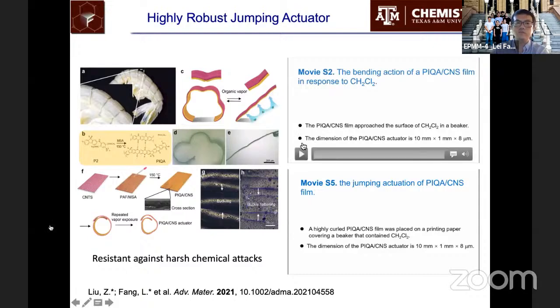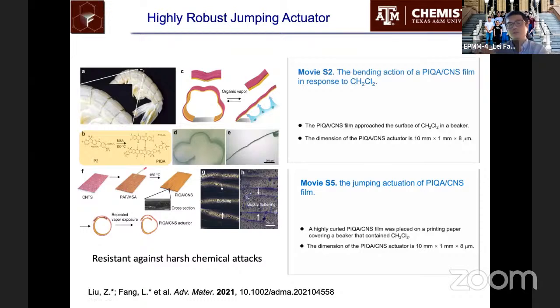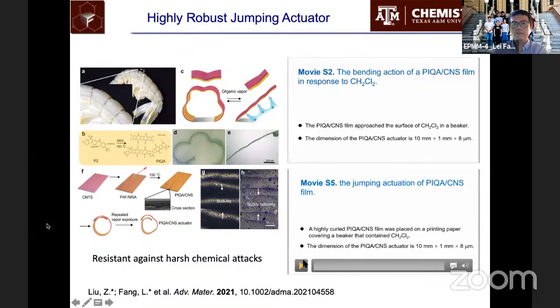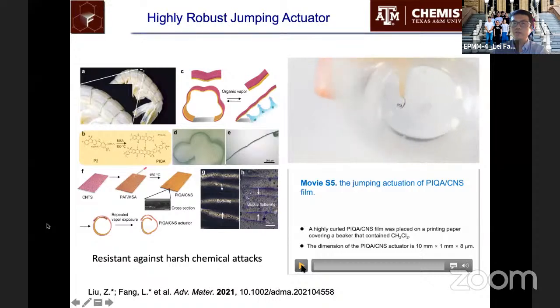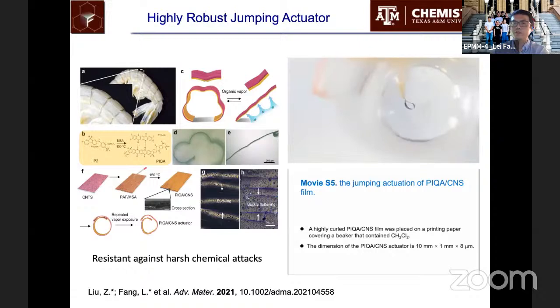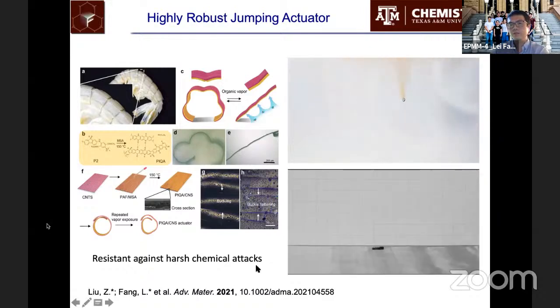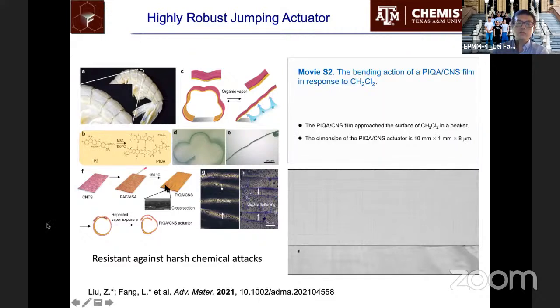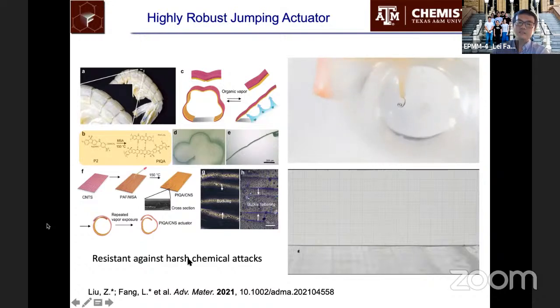For example, this actuator. This is a collaborative work where we put this ladder polymer on top of carbon nanotube sheets so that you could utilize the different expansion coefficient of the material versus carbon nanotube when you expose it to solvent vapor, and then that gives you this actuating process. I think this one shows that if you expose the film to external solvent, you can see a very big change of the shape due to the actuation process. And this could actually jump by itself due to the very strong force generated by this actuation. A very important aspect of this material is its resistance against very harsh chemical attacks, unlike most other polymer-based actuators, which you cannot really use against a strong solvent or strong acid or base.